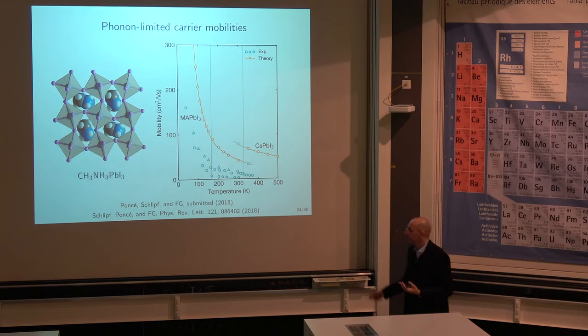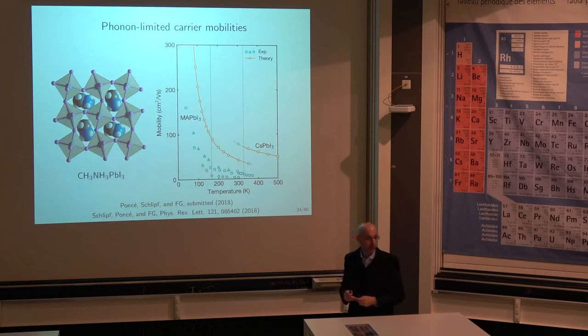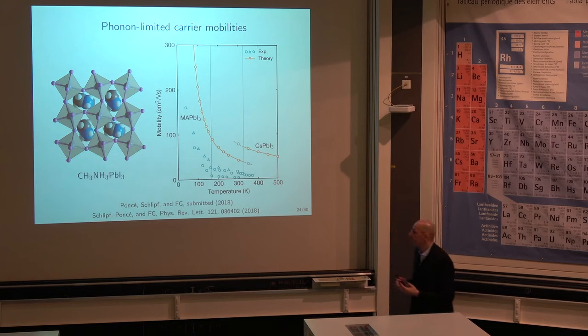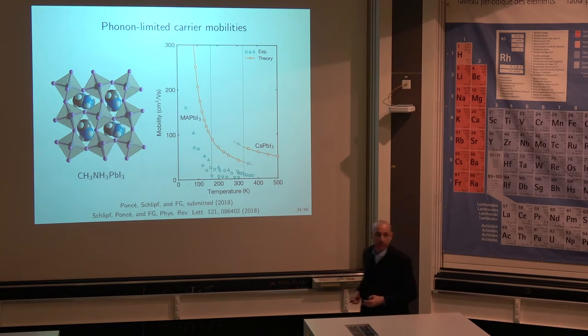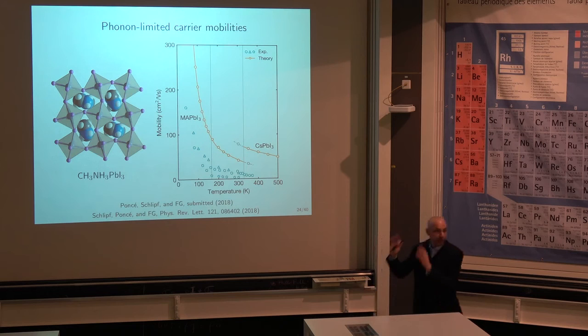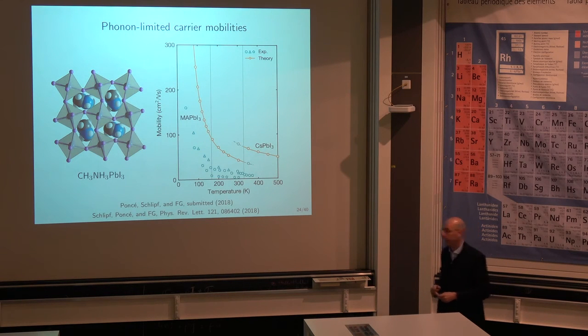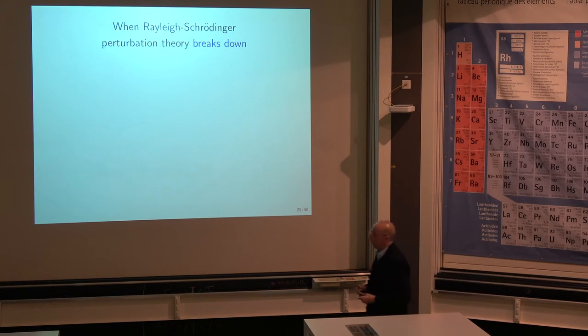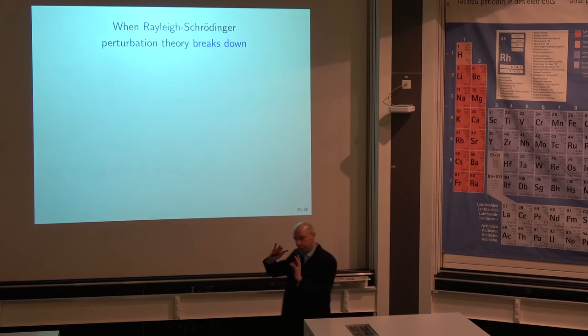So what we hope is that as the samples become cleaner, this data will creep up slowly towards this kind of theoretical upper bound. Essentially, this is a way for us to tell that we believe the maximum mobility you can achieve in these compounds is maybe of the order of 50 to 80 centimeters squared per volt second at room temperature. So if one wants to make transistors out of this, this is essentially the physical limit that they will face. And that closes the easy part of the talk.